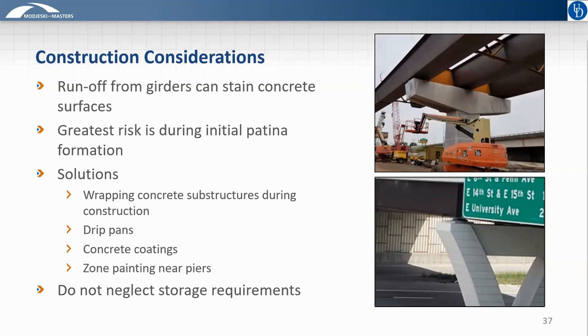Concrete coatings are helpful with this as well. And I mentioned before, you can zone paint the steel girders in the area of the pier to try and prevent that from happening. And don't neglect your storage requirements during construction either. There have been instances where girders were stored inappropriately on site, and that caused some difficulty in getting a good patina to form. And in that case, they were allowed to become submerged in floodwaters, which is not a good idea.